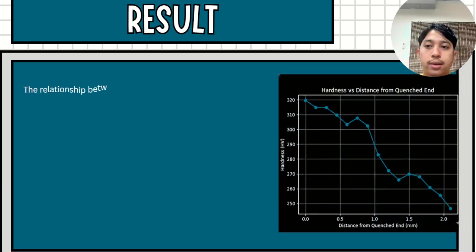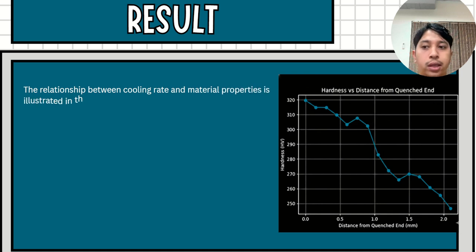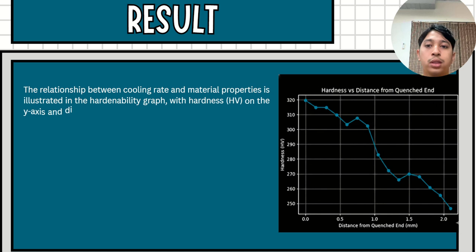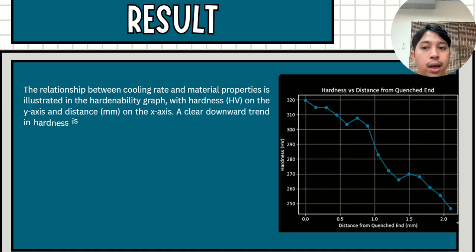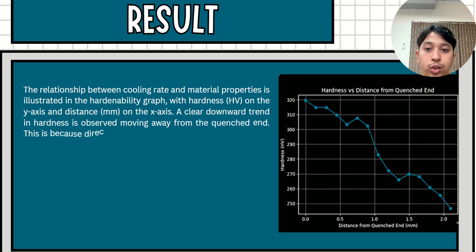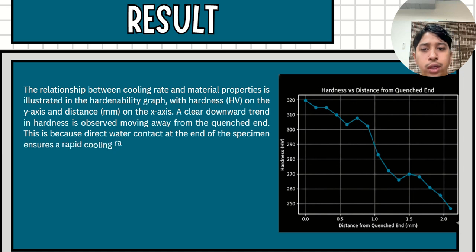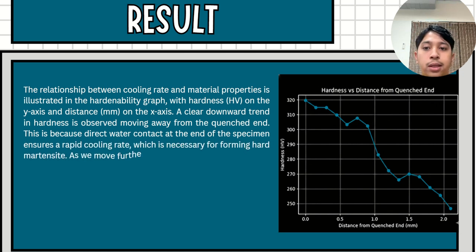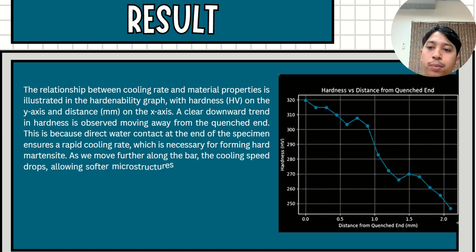For this slide, the relationship between cooling rate and material properties is clearly illustrated in the hardenability graph, where hardness in HV is plotted on the y-axis and distance in millimeters from the quench end on the x-axis. The graph shows a distinct downward trend in hardness as we move away from the quenched end. At the quenched end, the specimen is in direct contact with water, resulting in an extremely rapid cooling rate.